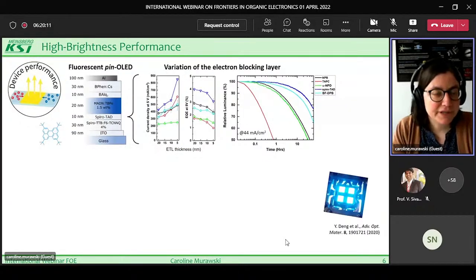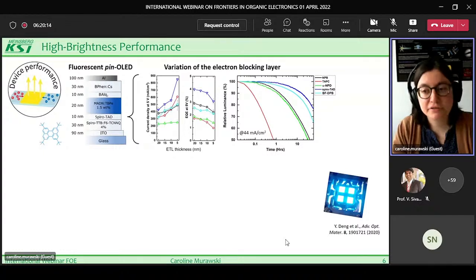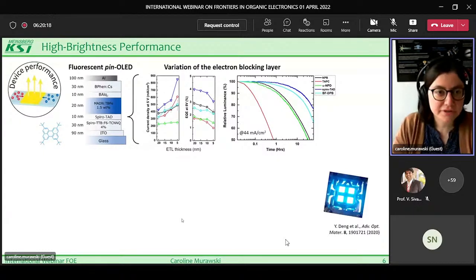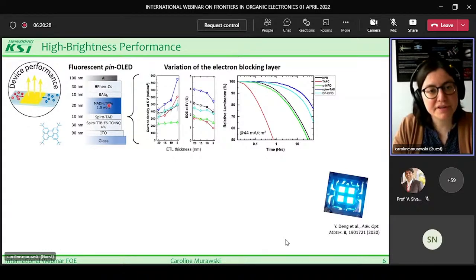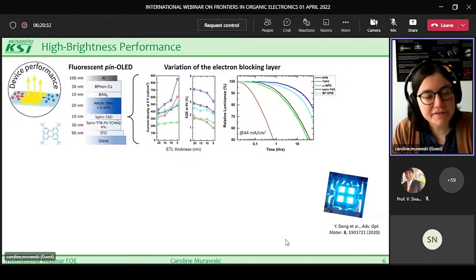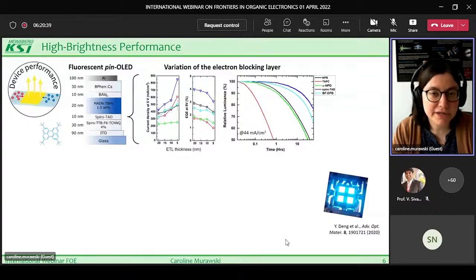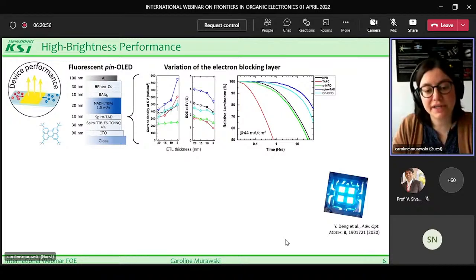In our work, we have predominantly concentrated on using fluorescent OLEDs, for some reasons. You can see the stack that we use most often, with slight variations. It comprises the fluorescent emitter TBPe. The reason for using fluorescent emitters is that we want to drive the devices at extremely high light intensities, where phosphorescent or TADF OLEDs would suffer strong efficiency roll-off. On the other hand, fluorescent emitters usually allow driving the devices at lower voltages, which is also important to get high luminance at low voltages.